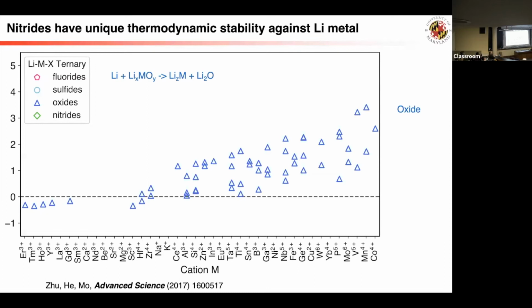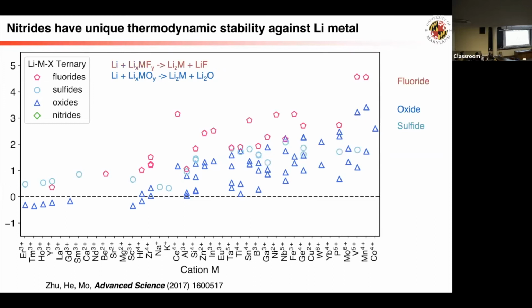But you can sort of see, for oxide, most of them are not stable, but some are stable. These are like the rare earth elements, so that's why a lot of good oxide solid electrolytes use a lot of rare earths. And if you see sulfide, none of them are stable. Fluoride is also not stable, right? People often think fluorides are super stable materials, but actually they're used as a conversion cathode, so they're not stable with lithium metal. And if you look at nitride, you can see a large number of them are stable with lithium metal.